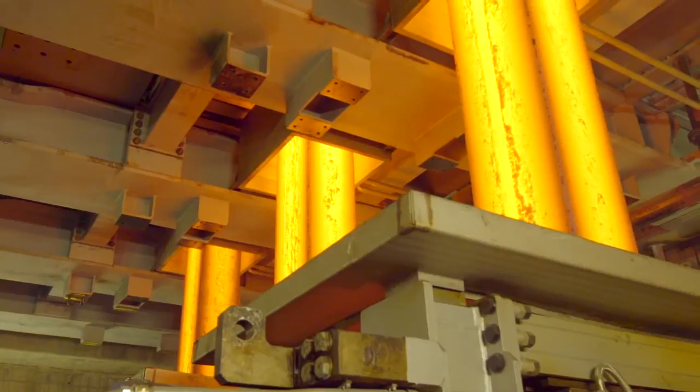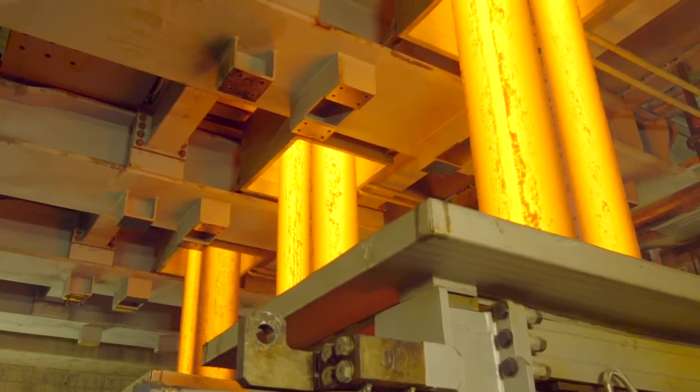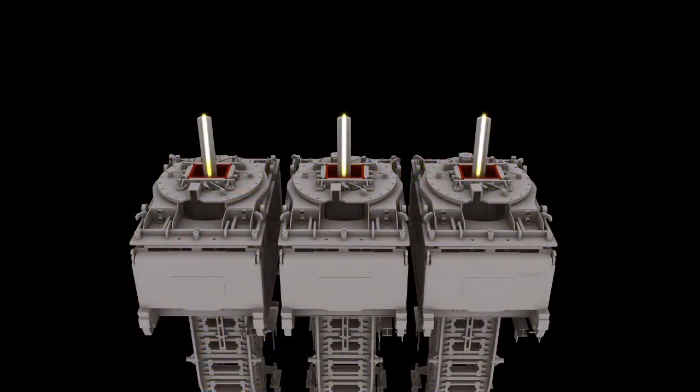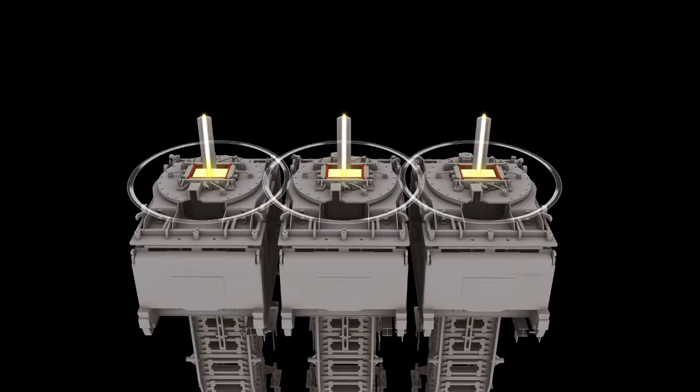The mold has a set of four copper plates that we clamp together and water cool. Mold powder protects the steel in the mold from oxidation. While in the mold, we utilize electromagnetic stirring to improve the solidification pattern.